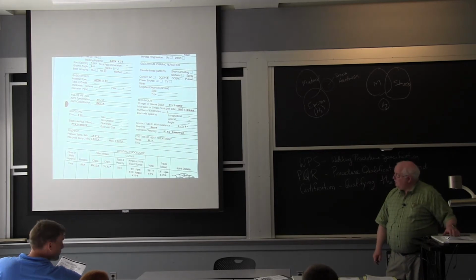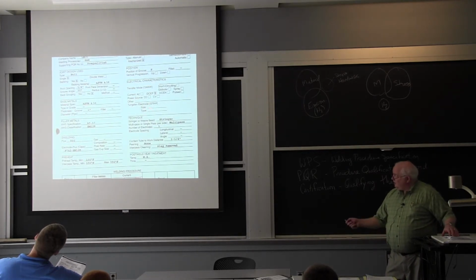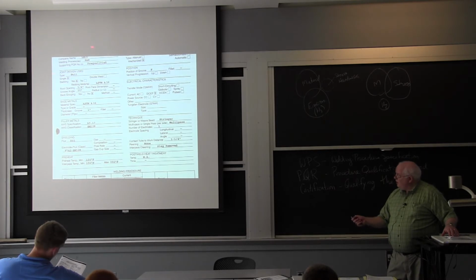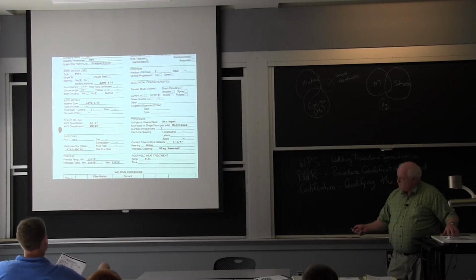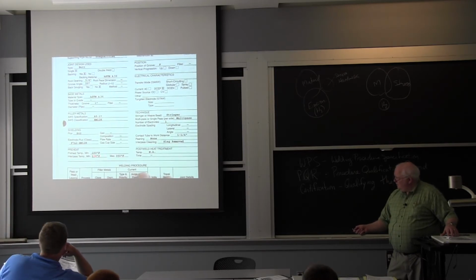Almost everything's filled in, very few blanks. It's not a tungsten process here, so they didn't fill in that. This is one where you have interpass cleaning. You've got to remove the slag. There's no post-weld heat treatment on this. Preheats are up to 150 degrees with interpass temperatures between 150 and 300.